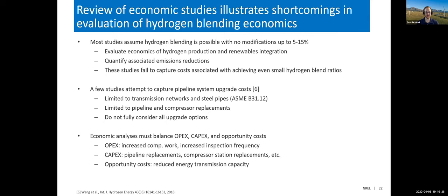There are a few studies that have attempted to capture these costs. There's one in particular from 2018 that I think is worth noting, that actually uses the ASME B31.12 design code for pure hydrogen pipelines to assess if existing natural gas pipelines could function with hydrogen and still be under code. But that study was really limited to steel pipelines and compressor replacements. There are a number of other components within transmission lines that need to be assessed. And then obviously distribution networks that operate at much lower pressures are something else entirely.